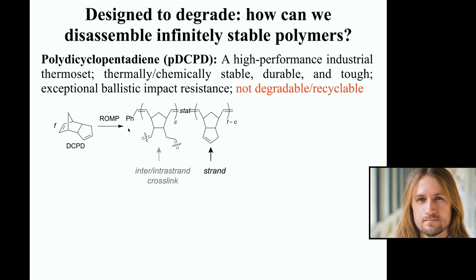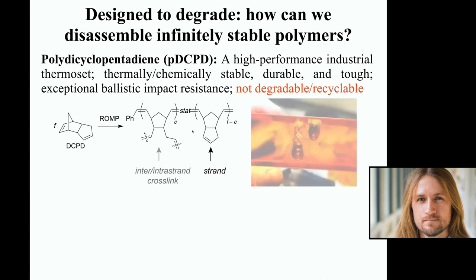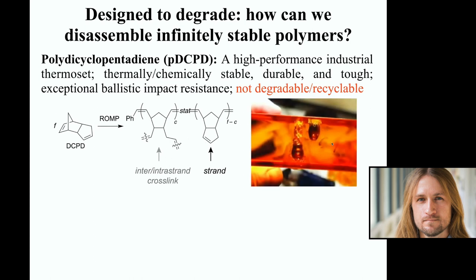PDCPD, like I talked about earlier, is a polymer network comprising monomers of DCPD that are polymerized using a technique called ring opening metathesis polymerization, or ROMP. And this reaction connects many of these DCPD molecules together into large strands that become cross-linked together. But the key thing to note is the entire material is made only of carbon and hydrogen bonds. There's no oxygens, there's no nitrogens, simply carbon and hydrogen. And the strong bonds that result from bonds of carbon and hydrogen in these systems make these materials very robust. And for example, this is a piece of polydicyclopentadiene that has been able to effectively stop a ballistic projectile, whereas many other types of plastics would simply shatter under such high nonlinear forces.